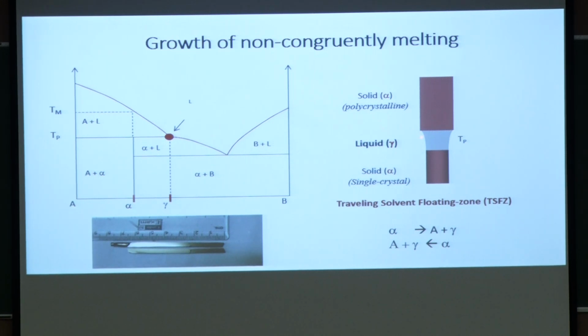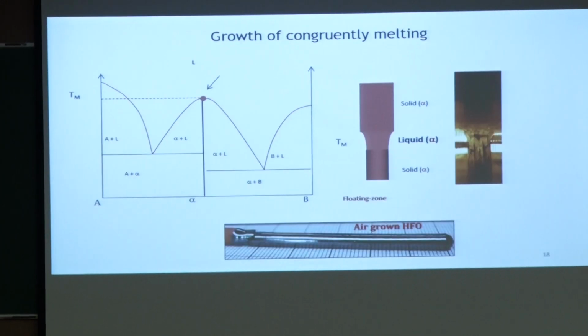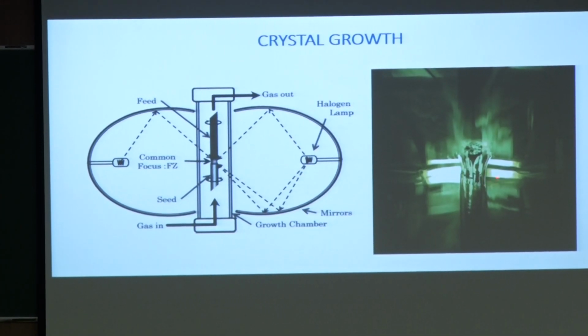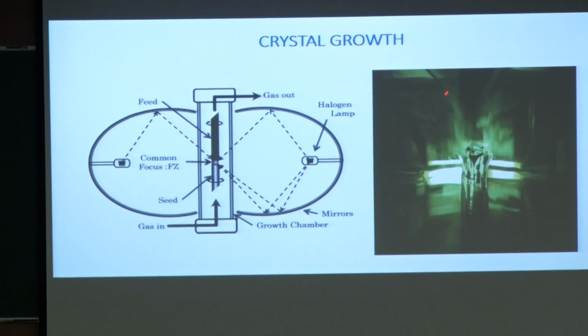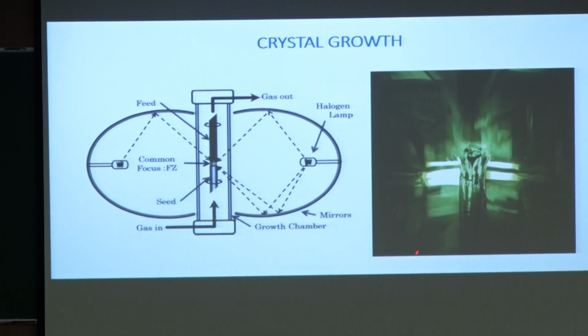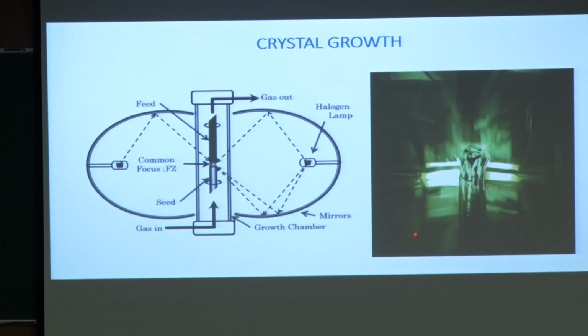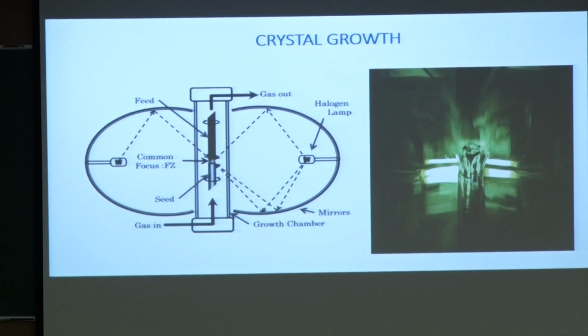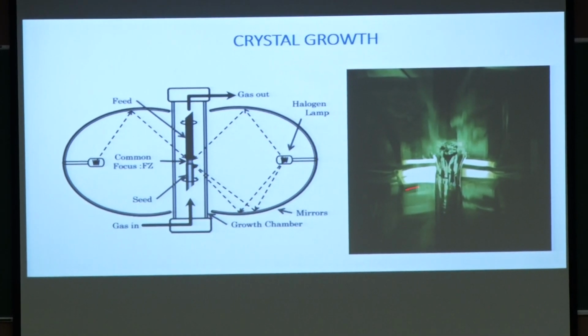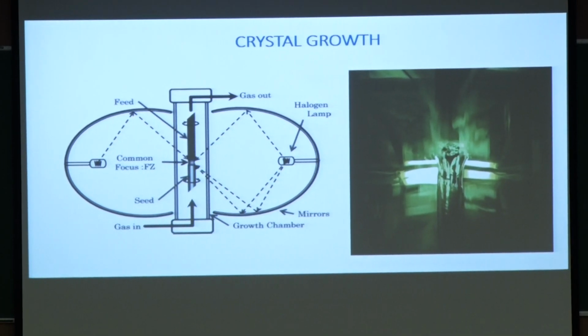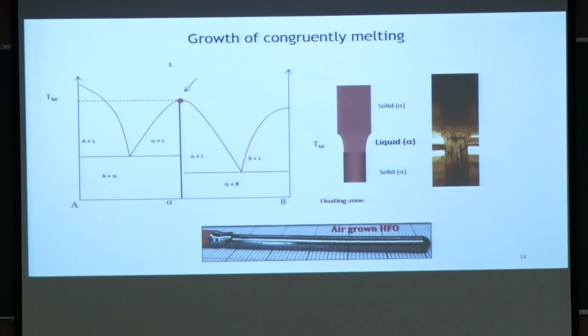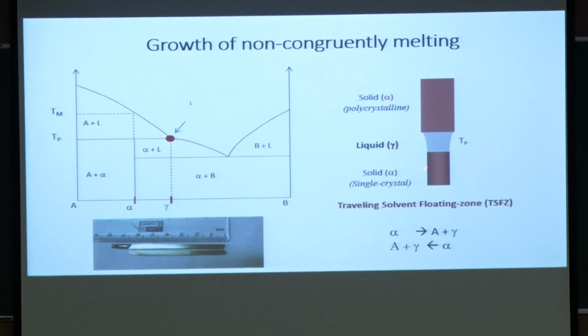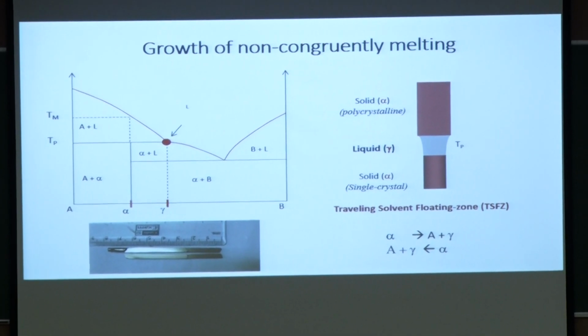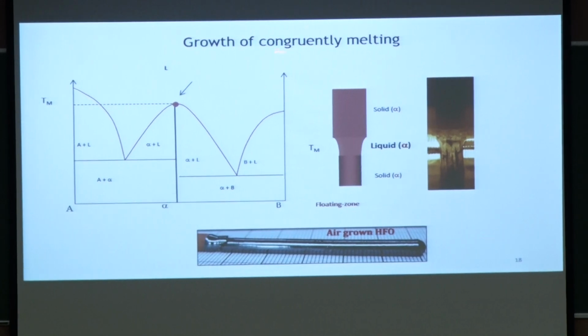So let me skip that part, except for mentioning that when you're growing this material, strontium 2 copper oxygen 3, this melt has a composition which differs considerably from the composition of the material which you have taken at the top, or the composition of the material of your crystal, which is Sr2CuO3. So basically what you have here is a flux. It's a material in which your parent material gets dissolved and gets exsolved at the lower interface. So at the lower interface you are exsolving the material, at the upper interface you are dissolving the material. So this is a dynamical equilibrium that sets in, and because of which you get these nice crystals.